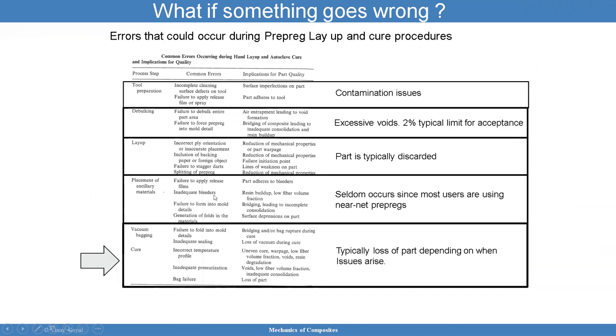And then here is the placement of ancillary materials in the manufacturing. Failure to apply release films, it's going to get stuck. Inadequate bleeders means that I don't have the resin. So just a second, I lost my train of thought. I apologize for that. But inadequate bleeders means that you may have resin buildup or low fiber volume fraction. Failure to form into mold details, that can, again, mean no consolidation there, and so forth.